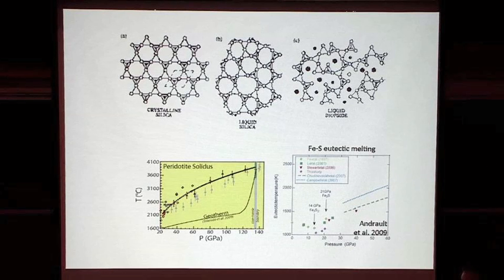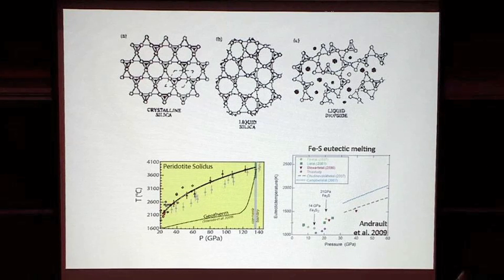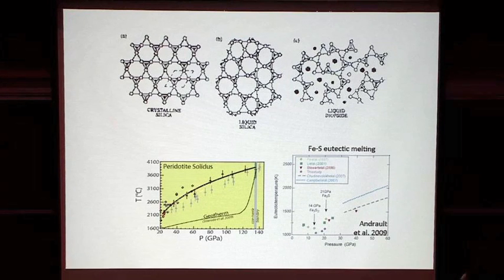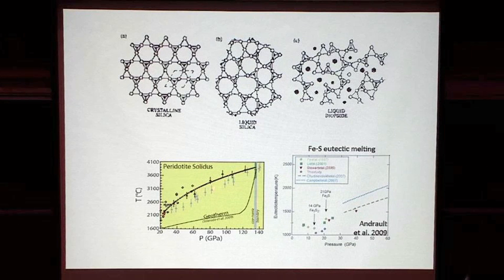But we care for a whole host of reasons, one of which is that, in fact, we do believe that there are melts stable along the geotherm in some relatively interesting places, not near the surface where the melting temperature is low. And that's the role of fluxes that have lowered the melting temperature of peridotite dramatically. And so that's one thing. And then the other thing, which we were sort of talking about just a moment ago, is that in the early Earth, in fact, melting of peridotite is completely relevant.